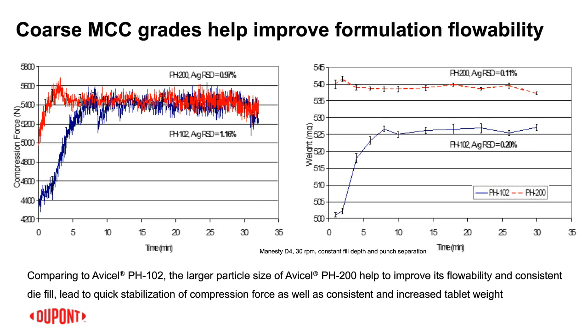And so how do you actually utilize the coarse grade to benefit the formulation, right? So we know coarse MCC can improve formulation flowability. Here's an example of how it actually helps. Compared to Avicel PH 102, the larger particle size and more spherical particle shape of Avicel PH 200 improve the flow property of the formulation and provide more consistent die filling. So you can observe a quick stabilization of compression force and also a consistent and increased tablet weight, right? On the left side shows a consistent compression force, and on the right side you're going to see a more consistent tablet weight.